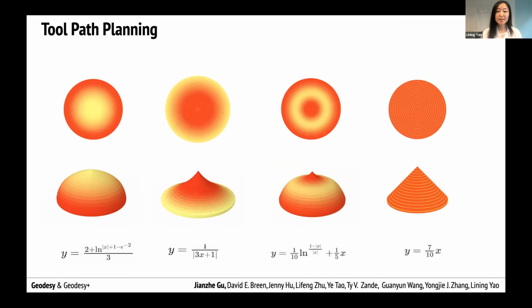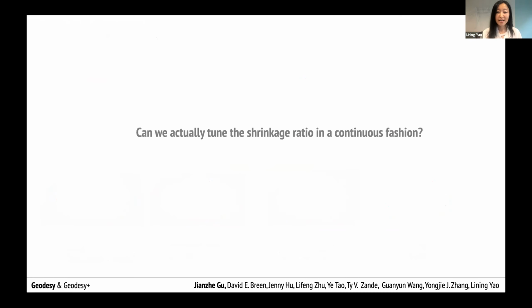And we have an assumption, the assumption that you can continuously tune the local shrinkage ratio that follows the printing direction. But can we actually tune the shrinkage ratio in a continuous fashion? Because what I just showed you are all kind of discrete, right? Origami, bending hinges, that sort of technique.